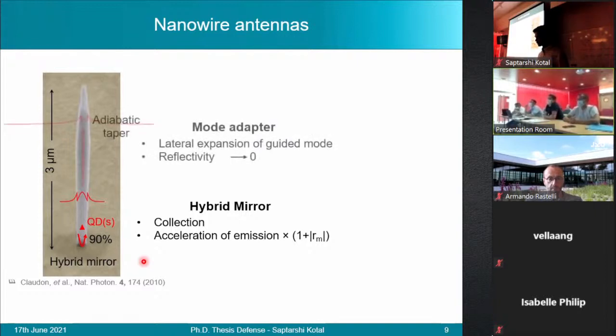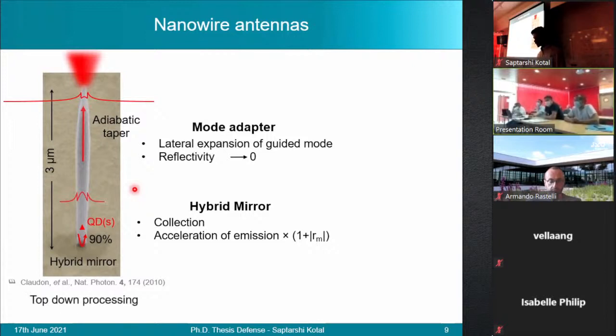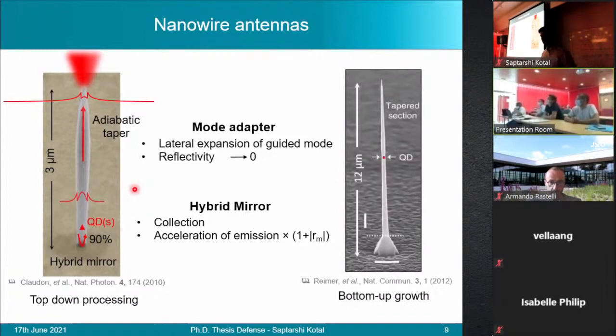On the other extremity, we introduce a taper in order to adiabatically expand the mode outside the nanowire in order to achieve a well-directional beam. Also, the taper at the top helps to eliminate the reflections from the top facet. Now, such nanowires are developed by a top-down etching process, and we call them needles. Similarly, they can also be developed by a bottom-up molecular beam epitaxy growth process as well.